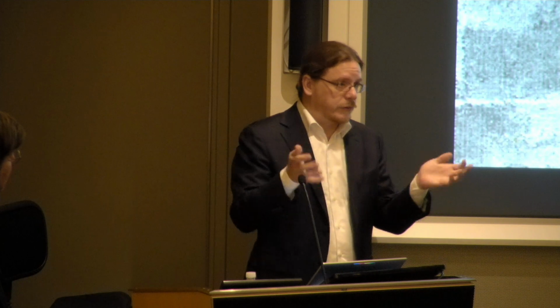It's also, by looking at the decay of the signal, able to tell us scattering and absorption coefficients. So we can imagine that we would have a map across the entire painting of things like the thickness of the varnish, the number of layers of varnish, the transparency, the scattering or the translucency, the absorption coefficient of the varnish across the whole painting, so that we'll have some idea in the future of being able to make physical models that will allow us to predict the appearance of the painting with a varnish removal before we actually do it.